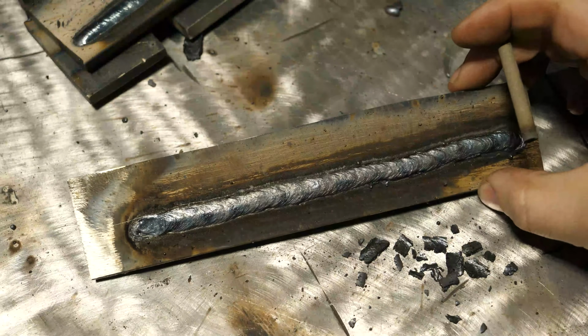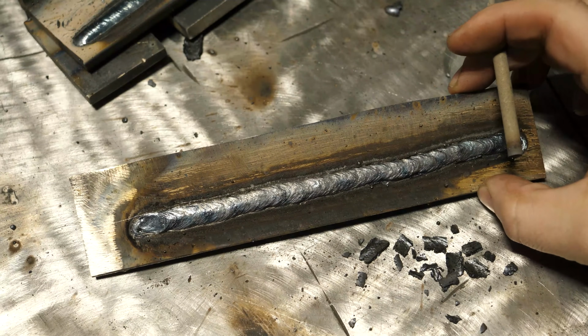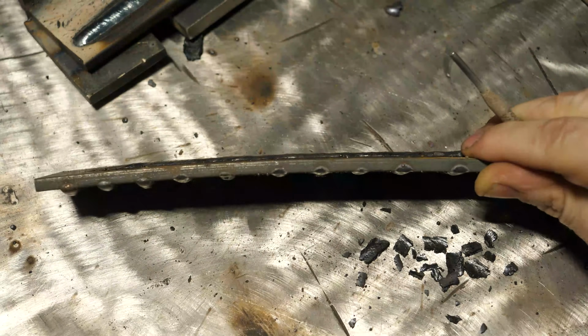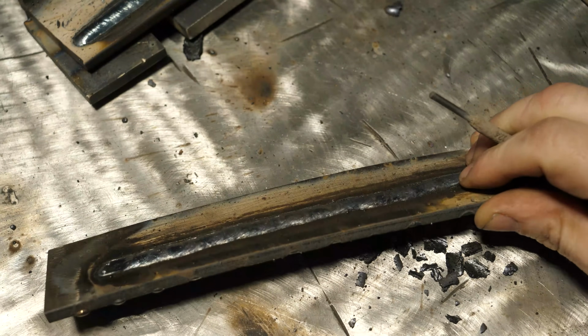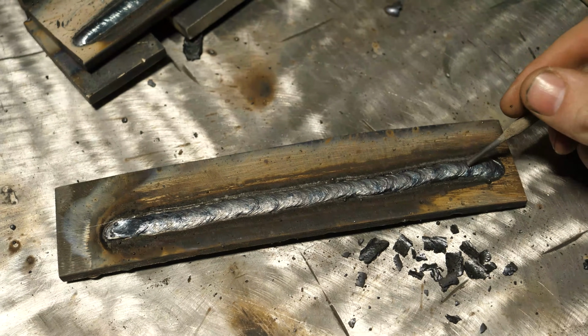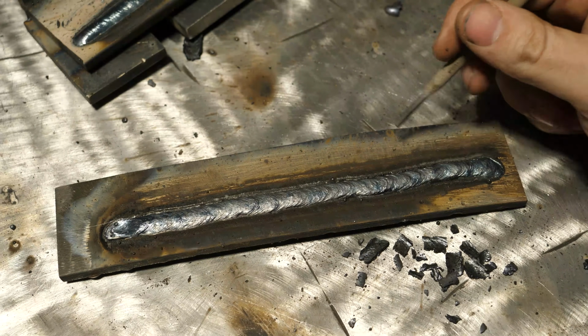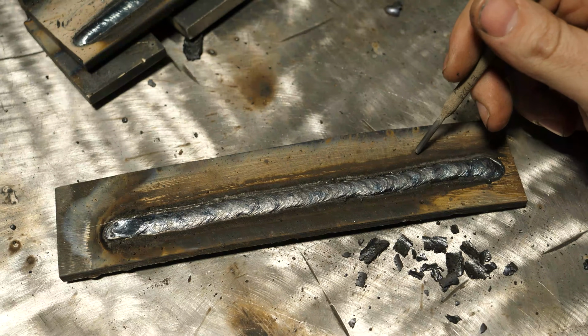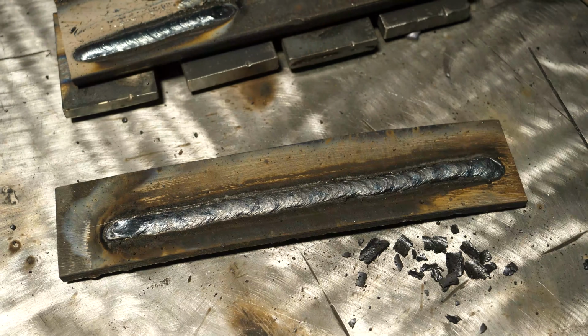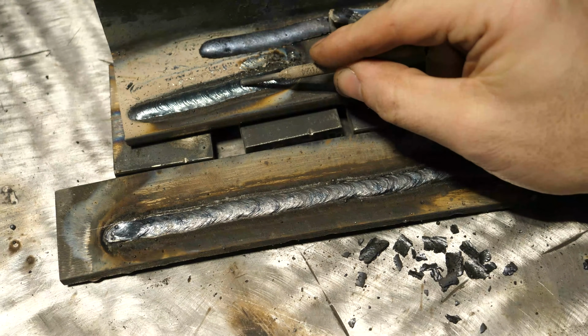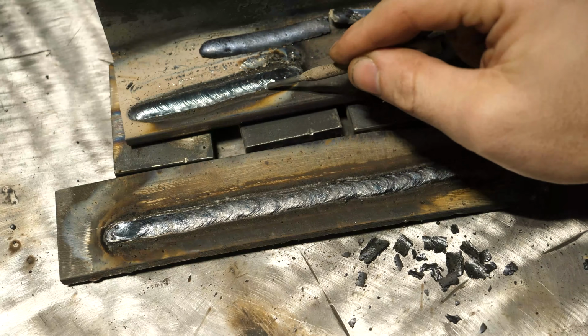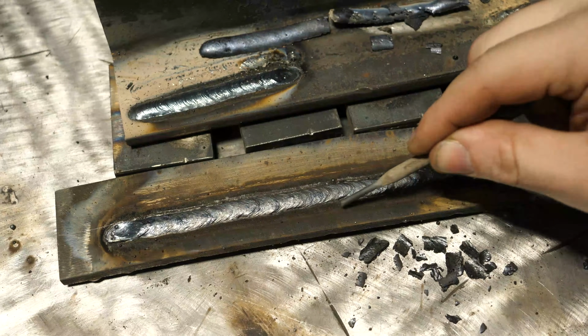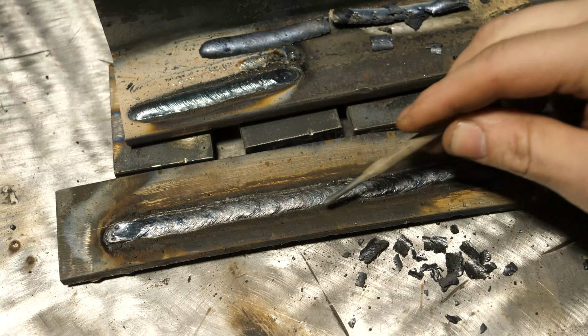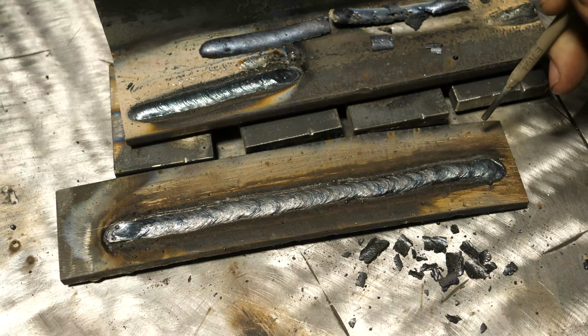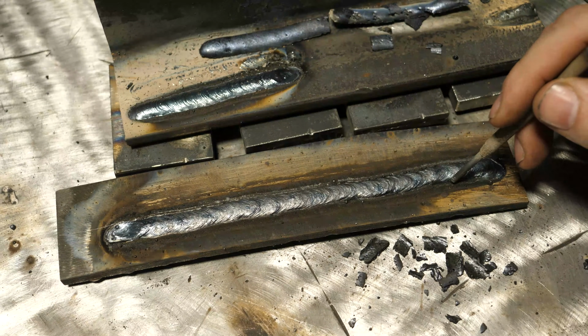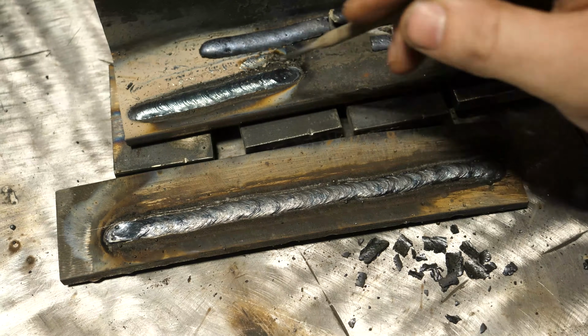So you can see bead appearance very wide, very flat. You can see how flat that is. 150 amps, I would say, is appropriate if you're trying to weld two pieces together. If you're just running a bead on plate, 140 amps, much better. Gets a little bit cleaner. The slag comes off the toes. Like you can see, there's still some in there, but very appropriate 150 amps for welding two pieces, a quarter or 3/8 together, but a little bit flat, a little bit wide.